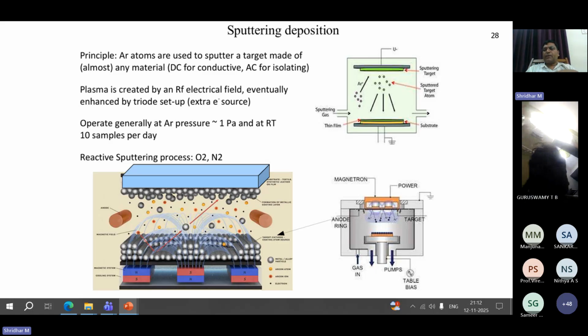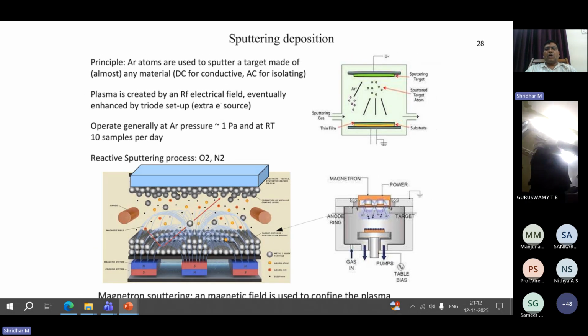If you deposit copper, what happens immediately? It turns into copper oxide. So that is why people will not go for it. But if it is a single layer, monolayer, or multi-layer, copper is okay. But when it comes to bulk copper, it easily gets oxidized by reacting with the oxygen.